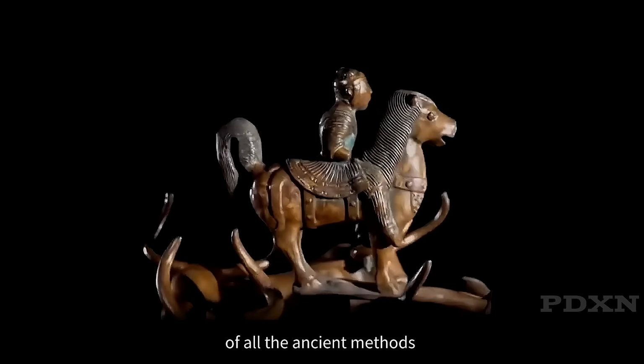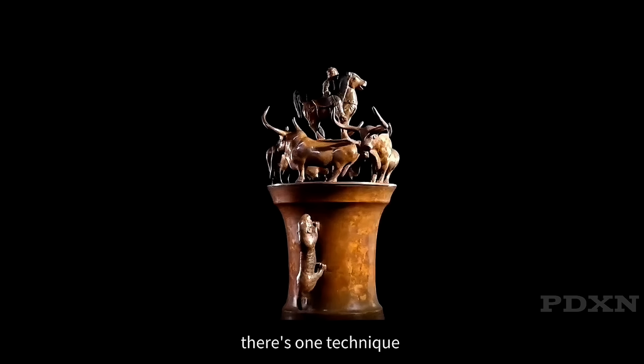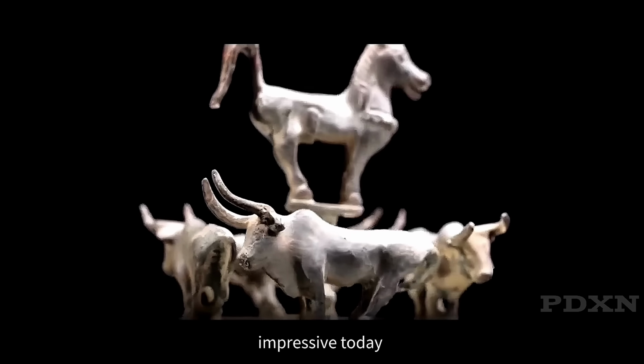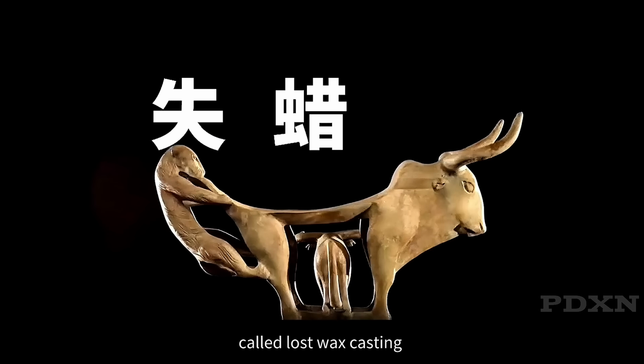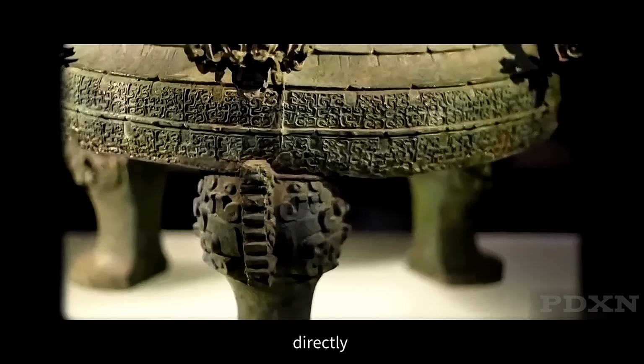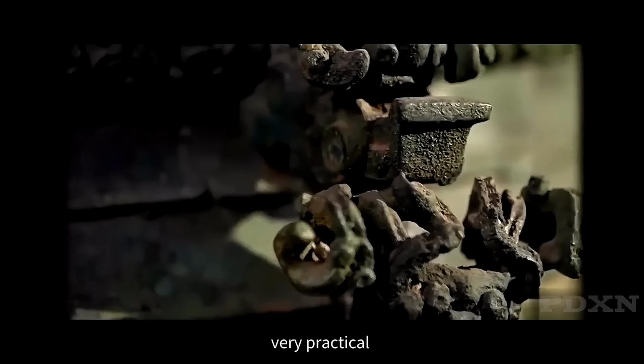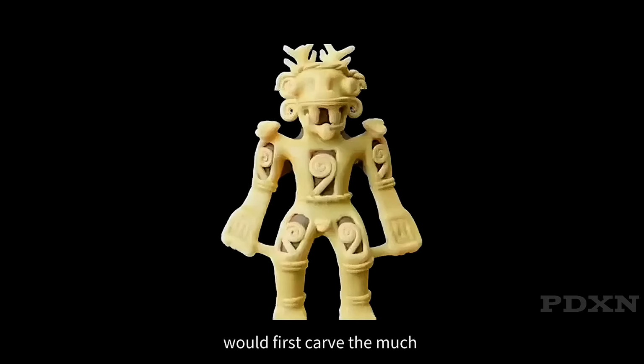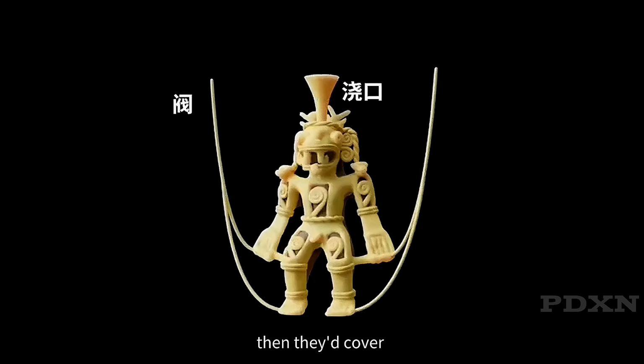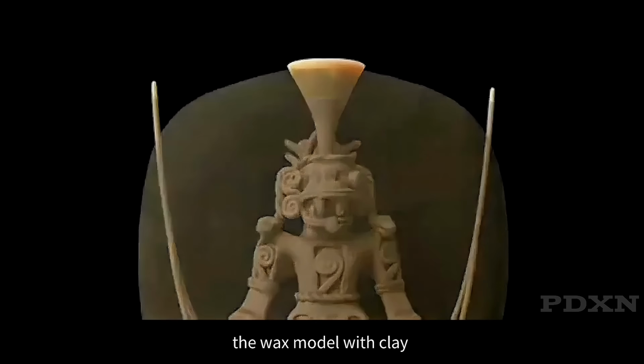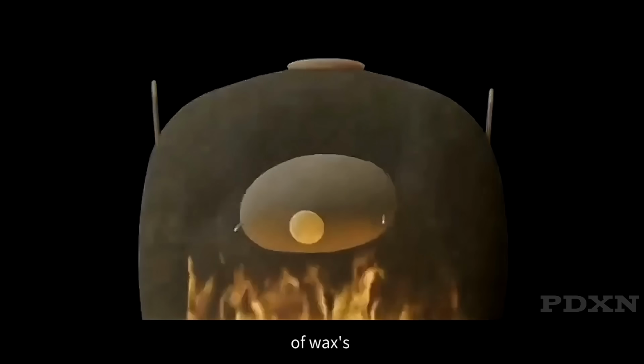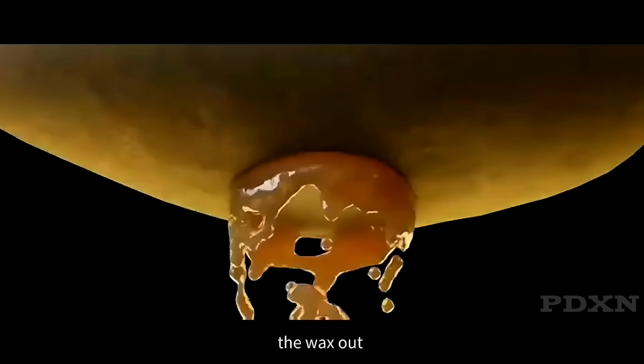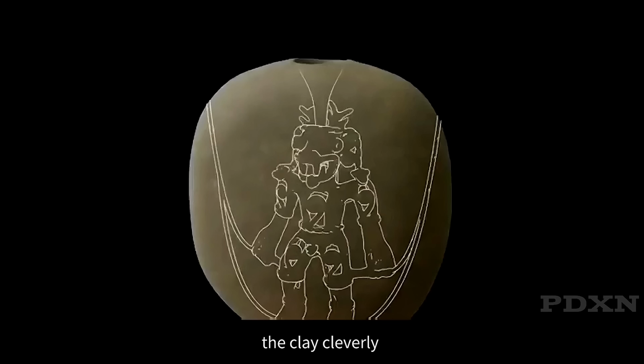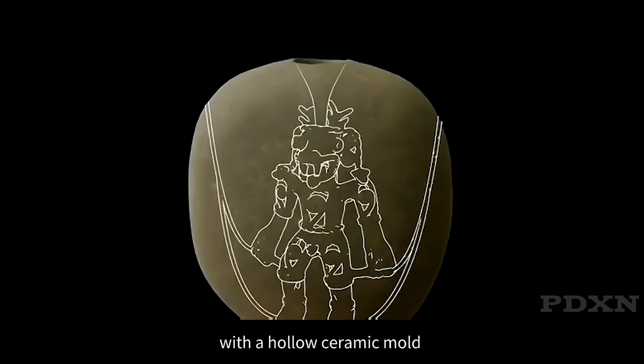myself. Of all the ancient methods for metalworking, there's one technique so brilliant it's still impressive today. It's called lost wax casting. To create intricate bronzeware, directly carving the metal itself isn't very practical. So the ancients would first carve the much softer wax. Then they'd cover the wax model with clay. And by taking advantage of wax's low melting point, they could melt the wax out, which also fired the clay, cleverly leaving them with a hollow ceramic mold.